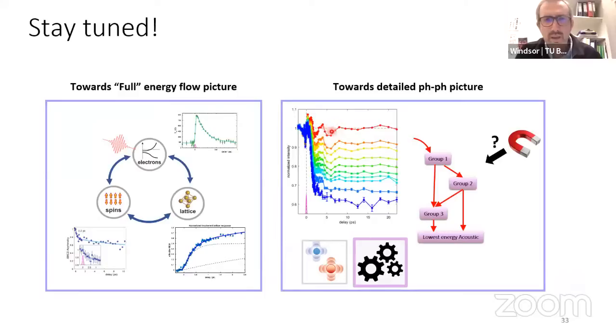I don't know if you can still see my mouse. There's a coherent beating which comes about because there is a specific phonon mode at the gamma point that remains populated for, I don't know, several picoseconds over a wide area in the sample. So it remains in phase. But this is a specific case, which is relatively common in these time-resolved experiments, because this kind of scenario of a coherent phonon is quite easily visible in many ultrafast experiments. So this is often discussed, and also it's a useful thing. Does this answer your question? Yeah, it does. Thank you.